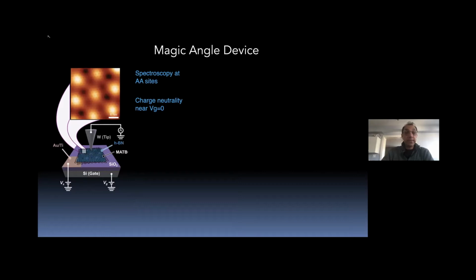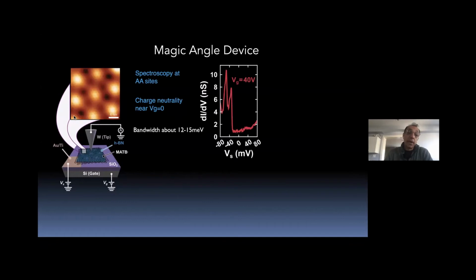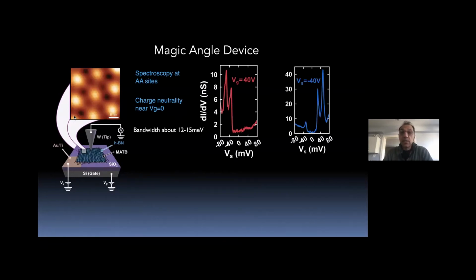So these samples are near a gate, and we can tune the gate in order to deplete and add electrons to the system. Let me first show you two spectra where the gate is such that we can fully deplete or fully occupy the flat bands in the system. The flat bands give rise to a large density of states, which gives you this peak in the dI/dV measurement as a function of tip-sample bias. These two sharp peaks are two flat bands which have two spin and two valley degrees of freedom within them, and you can see them below the chemical potential here, fully sharp, and above the chemical potential here, also fully sharp, and you can sometimes see the remote band also in these experiments.